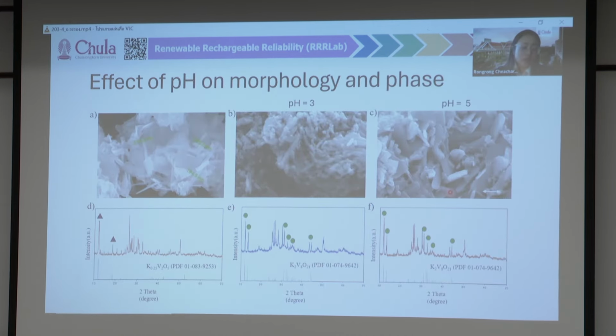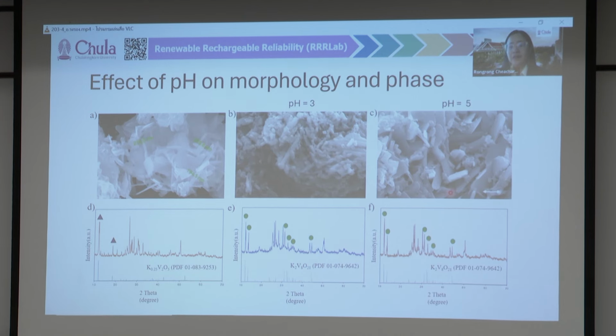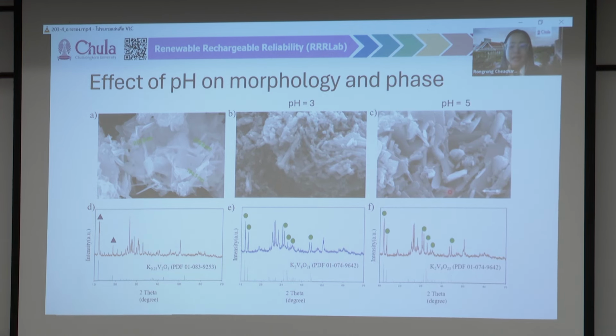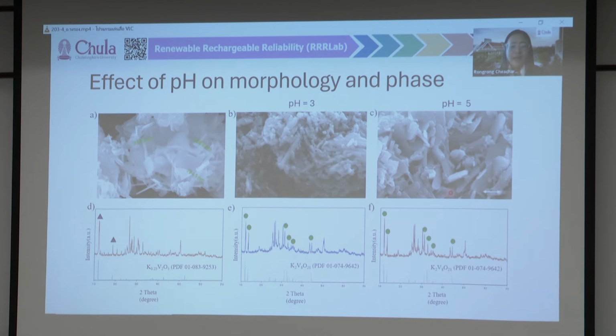And from reading papers, we think there's some effect of the pH during synthesis. So we explored pH adjustment during the synthesis, and looking at the morphology of these cathode materials, you can see that for picture A, we didn't control the pH.